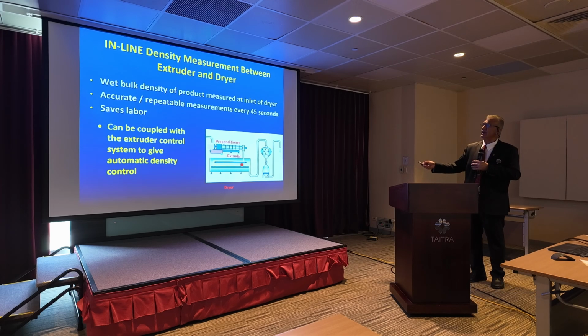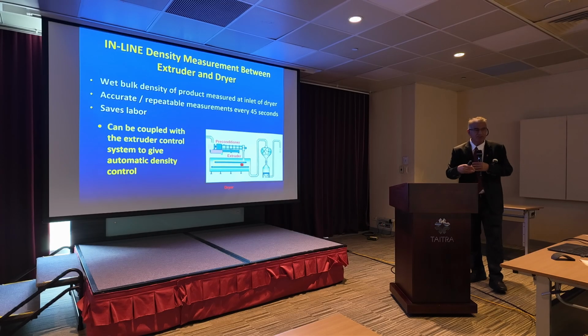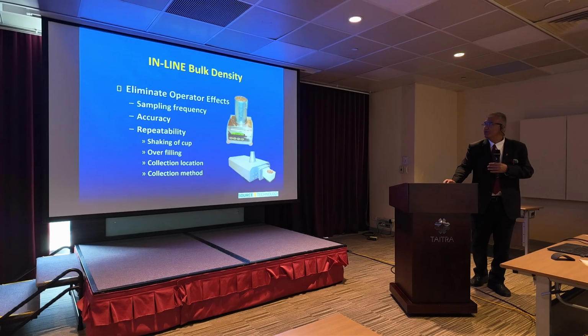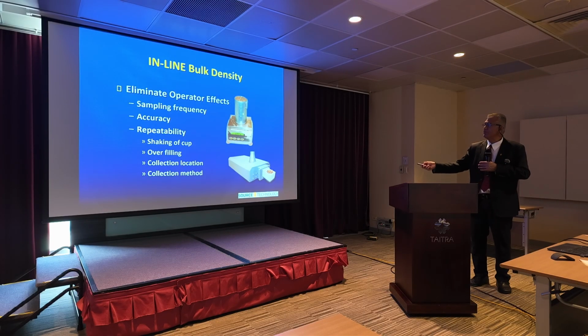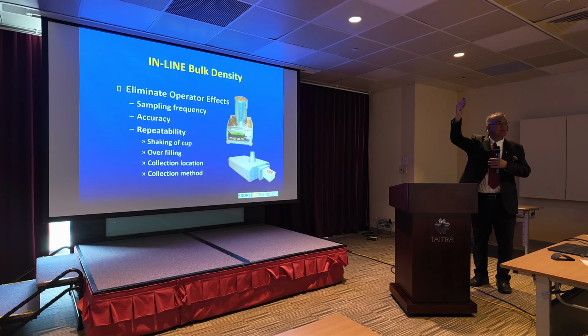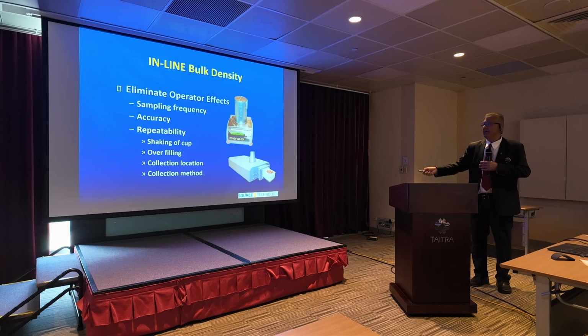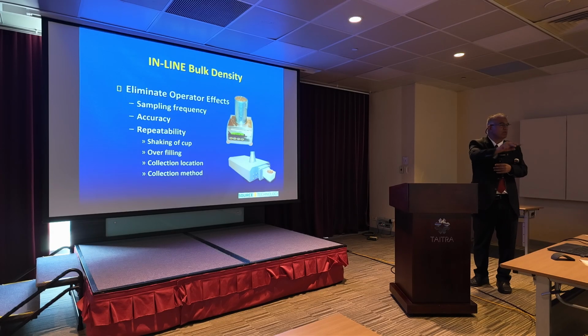Therefore, basically, inline density measurement, you can do coming from the preconditioner or coming from the extruder and then going to the dryer, because it gives you an accurate result every 45 seconds. Therefore, you do not have to wait for 2-3 hours. Traditionally, people measure it with this kind of system, and this sampling eliminates operator errors. Sometimes they just take one sample and keep it there because they don't want to go up and down all the time. They say, oh, we just took it. Sometimes people shake the cups, level it. If two people take the density, the results will be different because they both measure differently: collection locations, collection method. But this will give you everything online.